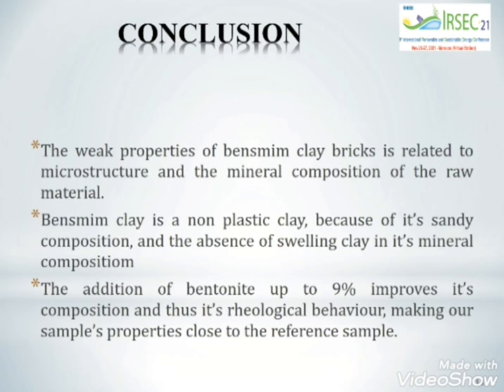Now let's sum up. We found that the weak properties of Bensmim clay are related to the microstructure and the mineral composition of raw materials. Bensmim clay is a non-plastic clay because of its sandy composition and the absence of swelling clay in its mineral composition. So we found that the addition of bentonite up to 9% improves its composition and thus its rheological behavior, making our sample's properties close to the reference sample.